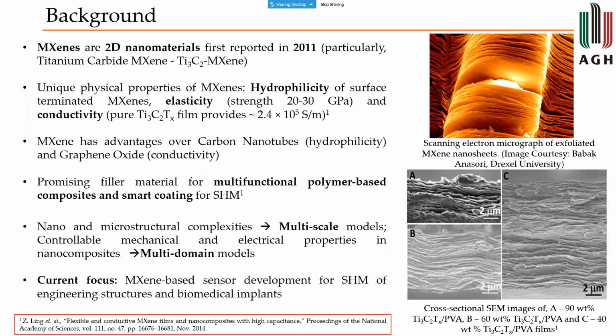And compared to carbon nanotubes, which form agglomerates or coagulate to form a group of nanomaterials, due to good dispersion and hydrophilicity, MXenes can be well dispersed, and you could have uniform structures being built from them. They have better conductivity than graphene oxide, and these are some initial points which led us to work on MXenes. And the complexities that we see with MXenes are from the nanoscale, because you need to model them from the nanoscale to the macro scale to have them respond well, and also compare the numerical models with the experimental results.